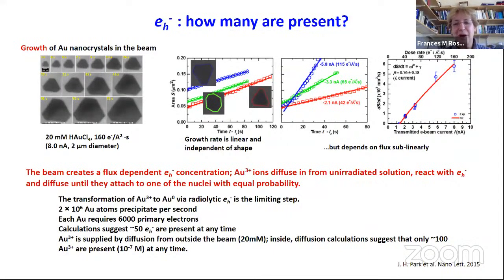Okay, so I want to show you this slide because it's possible to do some interesting calculations on radiolysis. And one of the ones that we found interesting was how many of these radiolysis products are there in your experiment. So specifically, let's set up an experiment where the electron beam illuminates an area. The area contains gold ions. We're using gold chloride solution. The beam creates hydrated electrons and they reduce the gold, and it forms a single island. And it's very easy to measure the volume of the island.